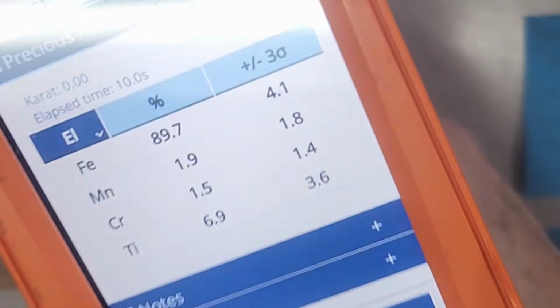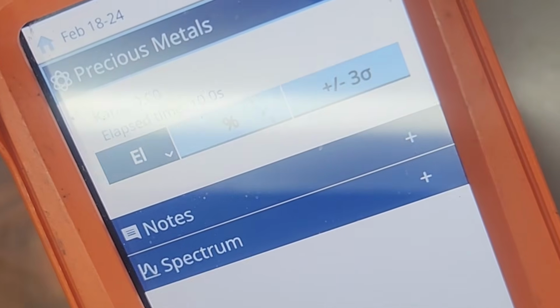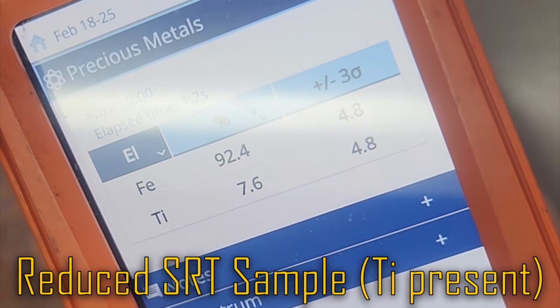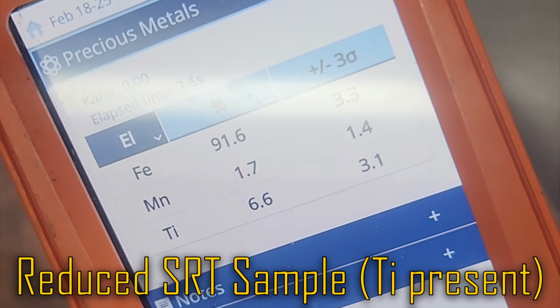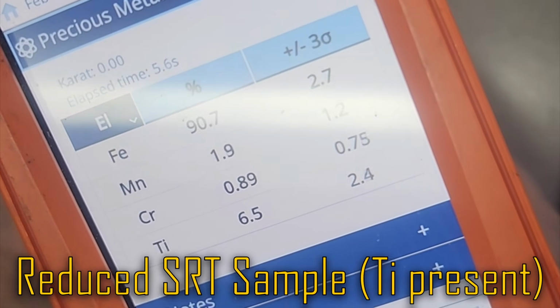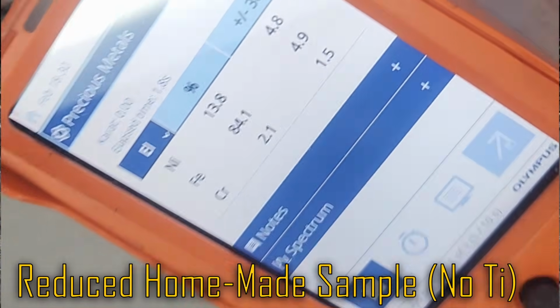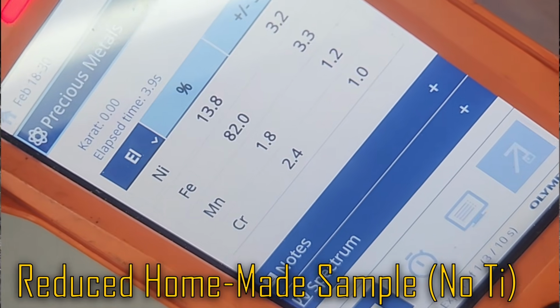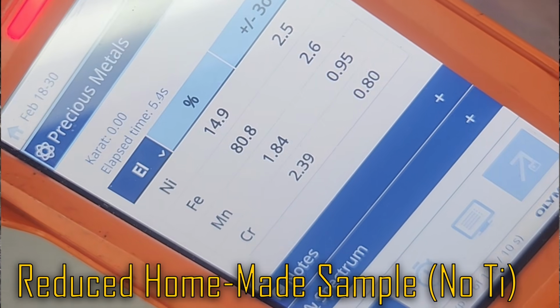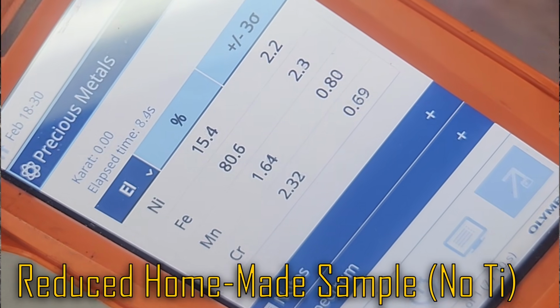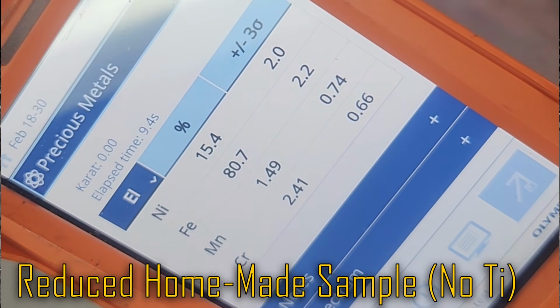Yes, we found titanium in 2 of the samples. They were actually reduced at higher temperatures. They were at the 1550C. So typically hydrogen doesn't reduce titanium. However, there has been some studies and research that does show that it can reduce when other elements are present, as they act as some function of a catalyst. But to be honest with you, the amount of titanium that was seen could have been an impurity because it was shown in the SRT product and not in the other simulant. So that's an anomaly we need to research.